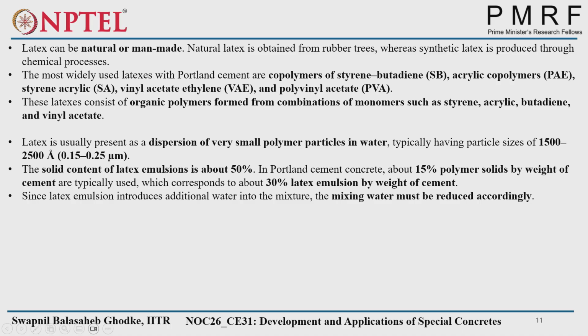So when you are using Portland cement concrete and you want to add 15% polymer solids by weight of cement, you cannot simply add 15% latex, because latex has 50% solids. At that time you have to add 30% latex to get 15% polymer by weight of cement. Because its solid content is 50%, only then do you get 15% polymer solids.